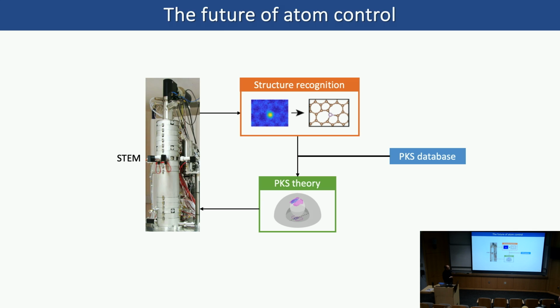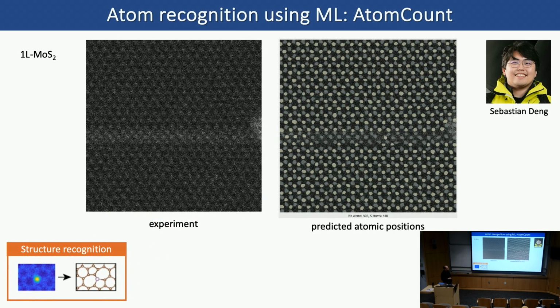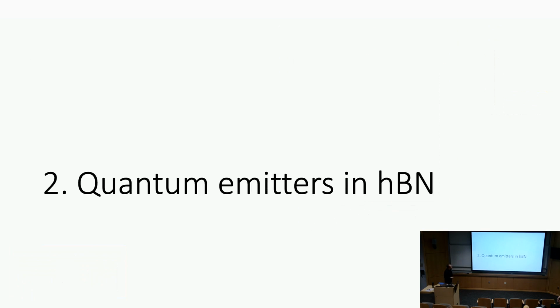So this makes the workflow of an automatic atom control. And you can see that the structural recognition is actually quite an important link. So one of my students here at Yale, Sebastian, is working on using machine learning to do atom recognition. So this is one example showing a monolayer MoS2 from experiment without any processing. We could use this model to predict where the sulfur atoms are, where the molybdenum atoms are, whether there are defects or not. So that's an ongoing project, but we hope we could fill this gap and make a complete feedback loop for controlling atoms using STEM.